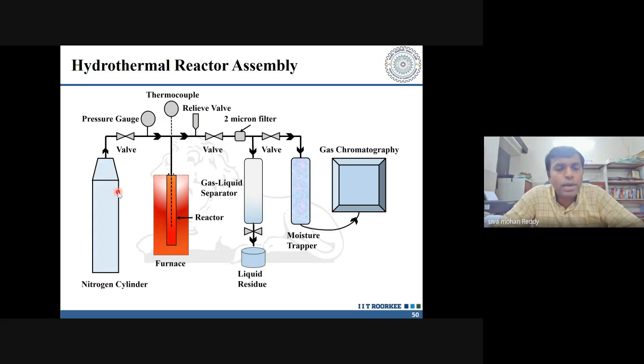Before you start the experiment, we make sure that all the lines associated with the reactor are purged with nitrogen, so that it is free of any oxidizing environment. Then we load the reactor with a known quantity of biomass, typically in the ratio of 1:10, and then we seal the reactor and place it in a furnace, where it is heated to the desired operating temperature of nearly 600 degrees centigrade.